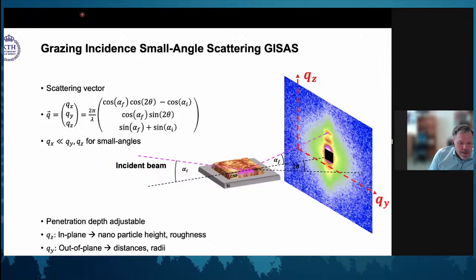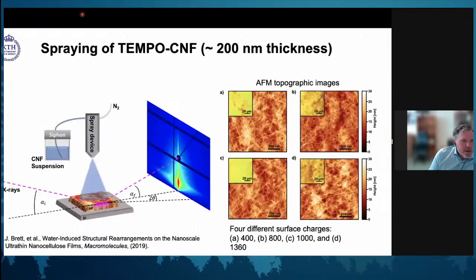So just taking this simple sample of spraying some fiber-based material. This is a spraying of TEMPO CNF, with different charges. So it actually means a couple of things. It means that it behaves differently because of the surface charge. And the second part is that the morphology of the CNF is changing. By doing this spraying, creating films, you can actually look at the films you get topographically. So that was what we have here. We have, in this case, four different charges. They look slightly different. You can, of course, with AFM start to try to characterize what you see here.